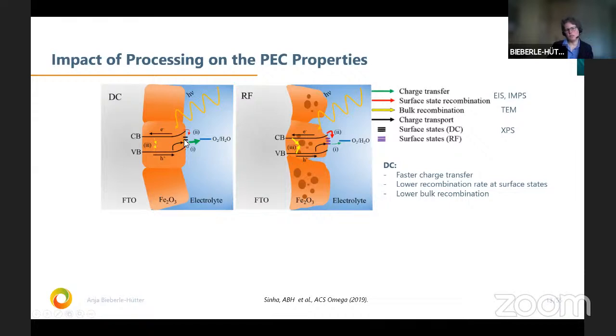We have also seen in the analysis that we have surface states. They're indicated here with this symbol, and we have put them in different colors here, because what we see from the analysis is that it looks like that we have even perhaps different surface states, and for sure different density of the surface states at the interface here. Surface state recombination is also different, more here than with the DC, and the charge transfer in the DC to form the O2 is faster.